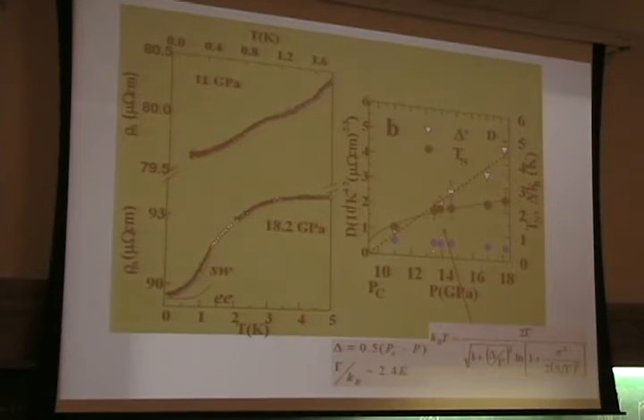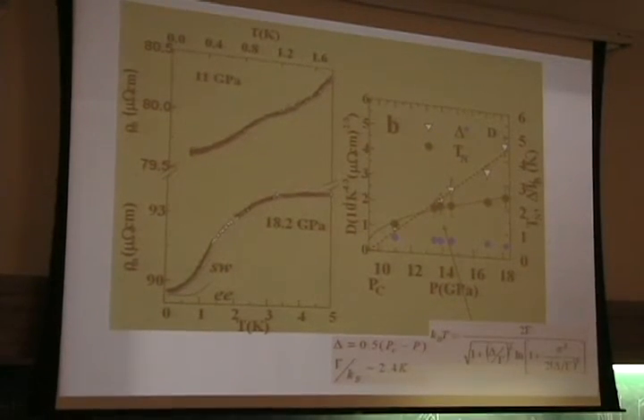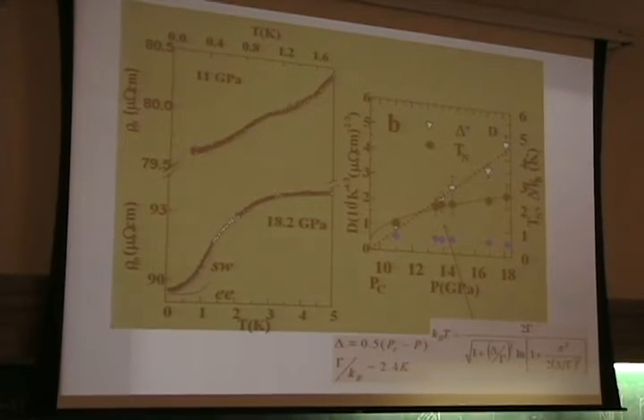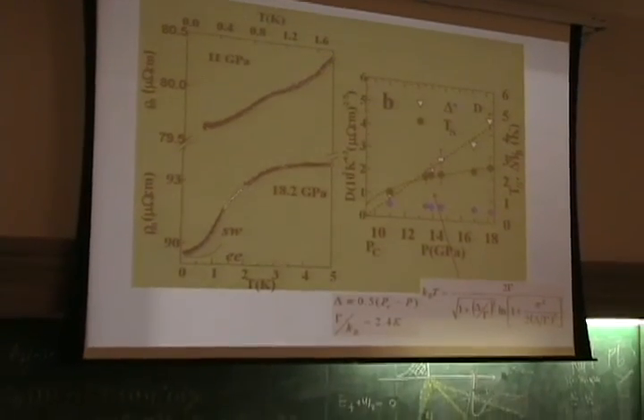And in this system, in general, you have a decrease. In the system I worked on in my thesis, it was easier because I did the substitution, and it was very easy to see that substitution with iron and pressure gives more or less the same kind of effect in the system. In general, you have a decrease of the C parameter and the A parameter, but a bigger decrease in the C parameter for this tetragonal system. So the volume decreases 10% more or less in some cases. So under hydrostatic pressure, the main effect is probably that the C parameter decreases more. Yes.